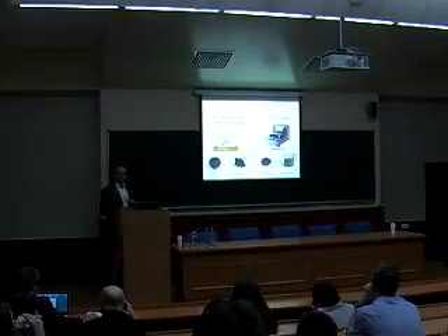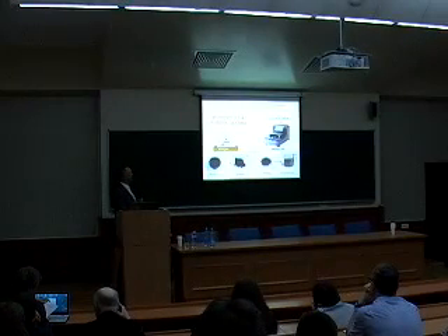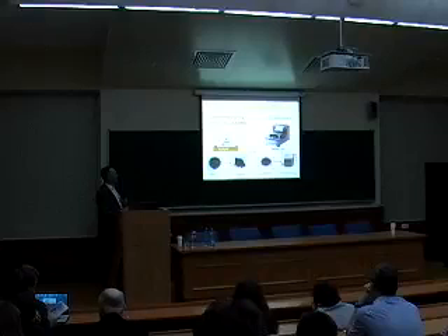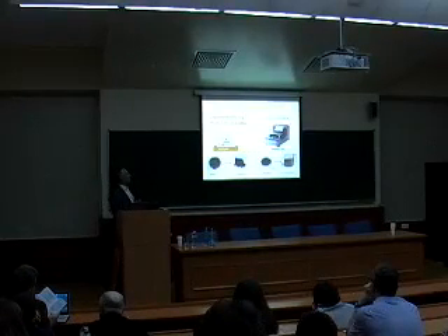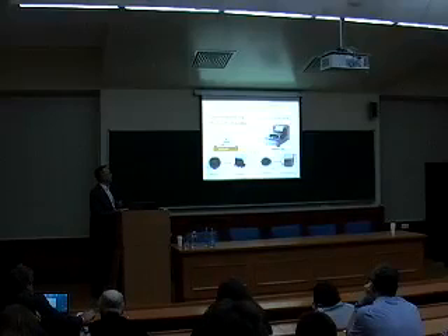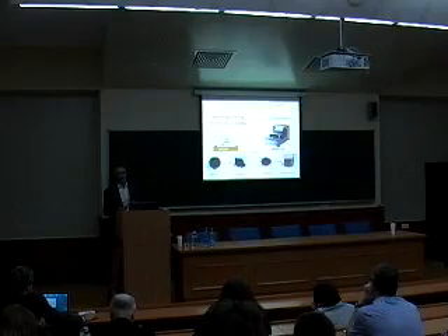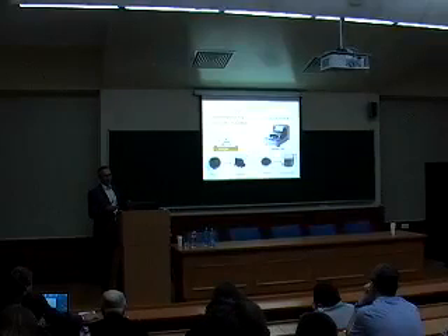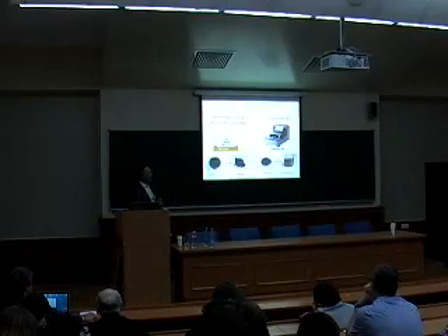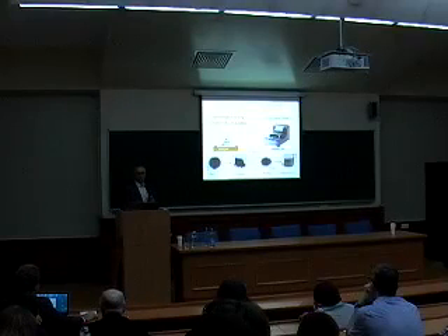For example, there is a very simple and, by the way, efficient method of preparation of silicon nanoparticles, porous silicon nanoparticles, which is based on electrochemical etching of crystalline, very pure silicon wafers in hydrofluoric acid solution. Then we obtain films, which can be detached from the substrate, crushed, and, for example, by using high energy mechanical milling, in a very simple and fast way we can obtain a lot of what I call liquid silicon. These are very concentrated silicon solutions, and the nanoparticles are not, of course, well shaped because they are porous and crushed mechanically. But this material is very convenient for different purposes. I will show afterwards how it can be investigated in a biomedical way.